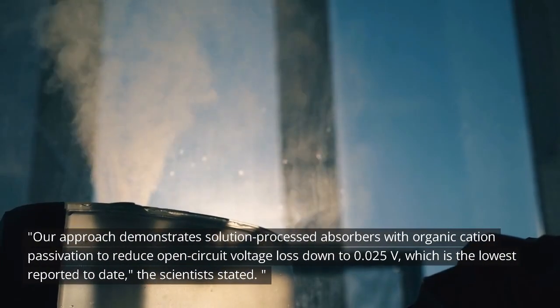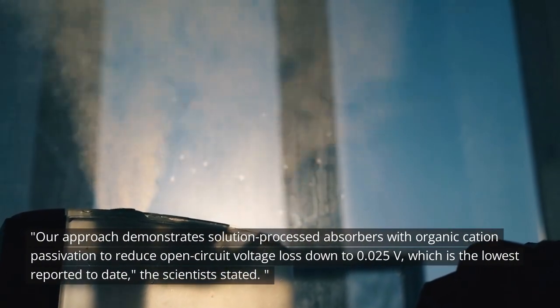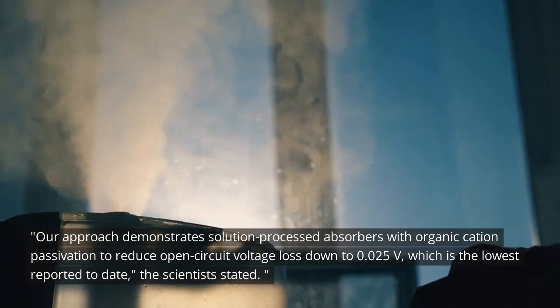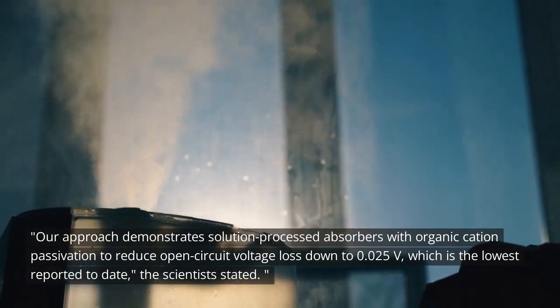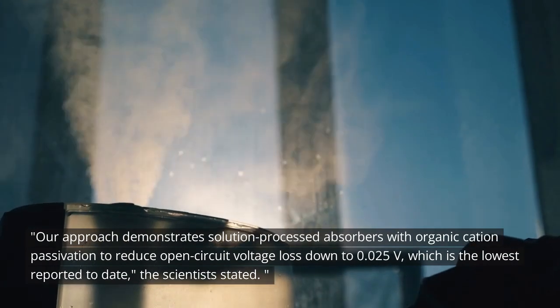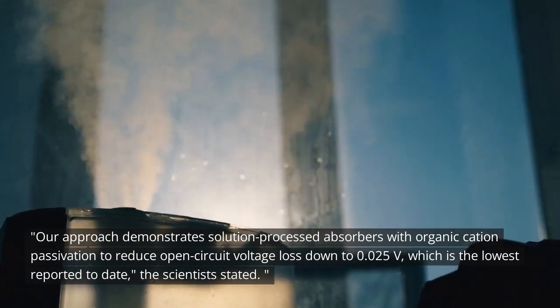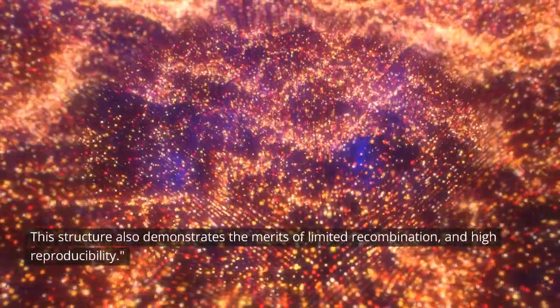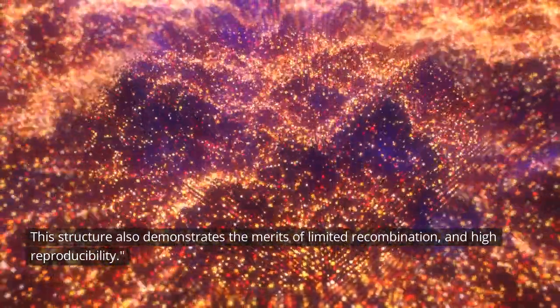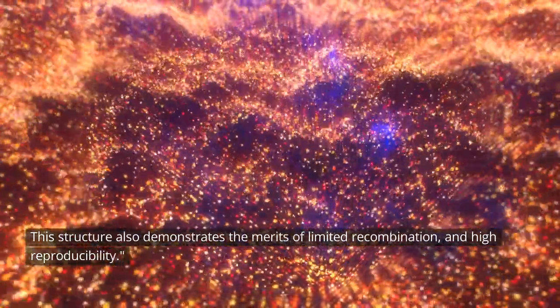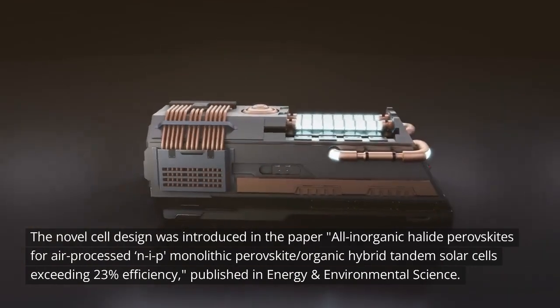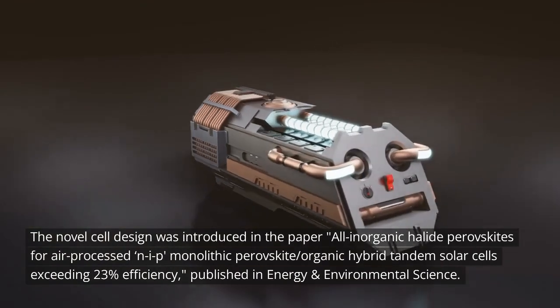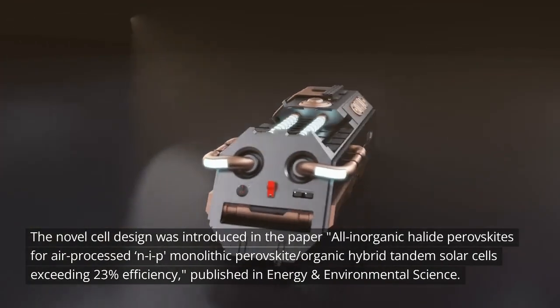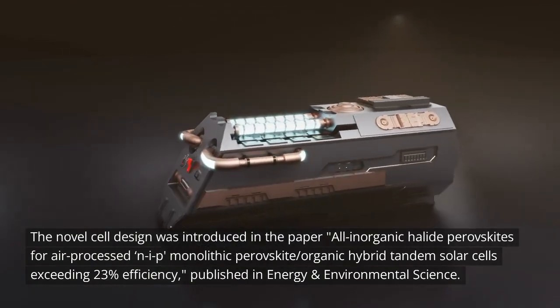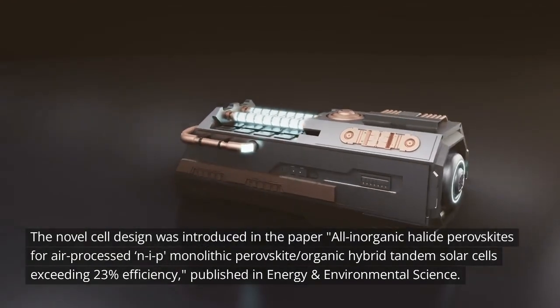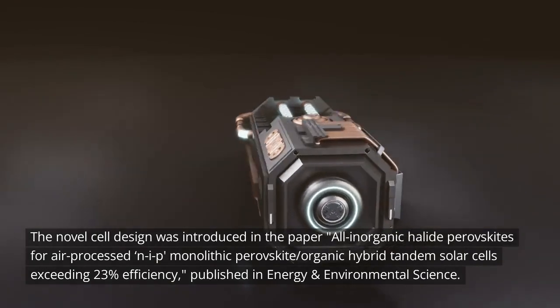"Our approach demonstrates solution-processed absorbers with organic cation passivation to reduce open circuit voltage loss down to 0.025 V, which is the lowest reported to date," the scientists stated. "This structure also demonstrates the merits of limited recombination and high reproducibility." The novel cell design was introduced in the paper "All-Inorganic Halide Perovskites for Air-Processed NIP Monolithic Perovskite/Organic Hybrid Tandem Solar Cells Exceeding 23% Efficiency," published in Energy and Environmental Science.